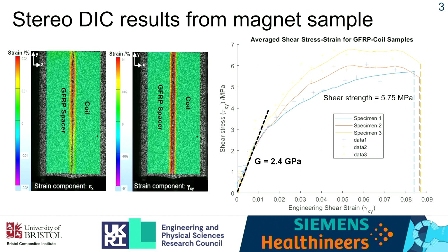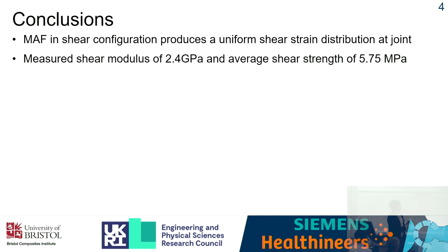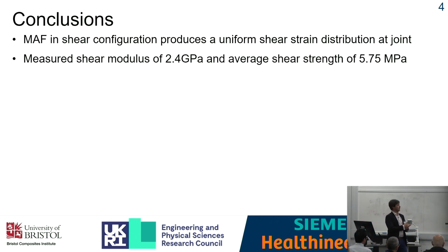And I have also looked at the neat epoxy with steel coupons to see if the epoxy by itself acts differently to when it's in these magnet coupons. In conclusion, I get a very nice shear distribution across the interface, which allows me to measure the shear modulus and shear strength.